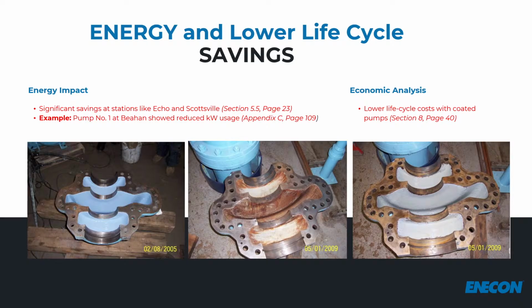You might have a couple of pockets in there where maybe the corrosion did come through. But what's nice is localized touch-ups could be done and the pump could be put back into service in a relatively fast fashion. So you can see here, it held up really well. And you're going to have a lot better than having leaks, having seal issues, having corrosion. So it really does work out well to protect that split case pump.